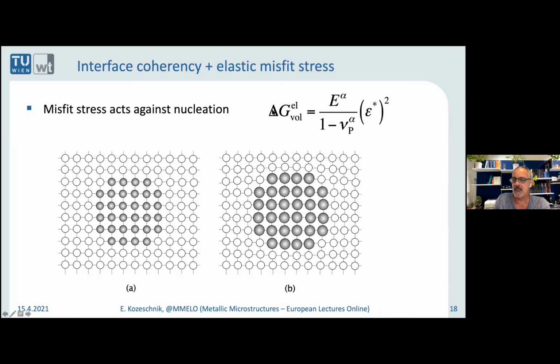It can be easily evaluated: the elastic modulus, the Poisson ratio, and this epsilon star is the linear misfit of precipitate and matrix. It doesn't matter whether it's larger or smaller because we have the cube here and the energy is always a positive value. And that will always act against nucleation. And I think in most cases, you definitely have to take these elastic stresses into account, because most nucleation processes are more or less occurring in coherent structure.